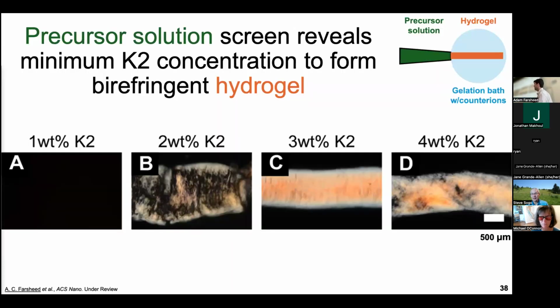So using this technique, I went ahead and screened a series of first precursor solutions, starting at 1 weight percent K2 dissolved in water, all the way up to 4 weight percent K2 in water. And what we saw is that 3 weight percent K2 seemed to be kind of the perfect point where we get nice polarized light coming through, and also a noodle that looks like a noodle and not like a blob in the 2 weight percent case. And so because of that, the remainder of the study was done at 3 weight percent.